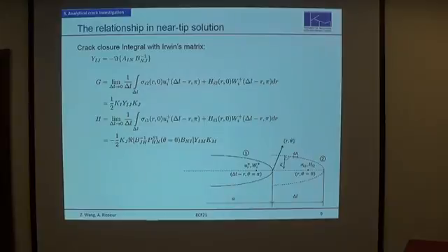Analogous to the Irwin crack closure integral, we can also see that the energy term can be performed as phonon energy as well as phason energy at the cracked ligament, with the jump of displacement at the cracked surfaces in a virtual crack opening process. We can insert the Stroh solution into this integral, and we can get this relationship: the first energy release rate term and the second energy release rate term.